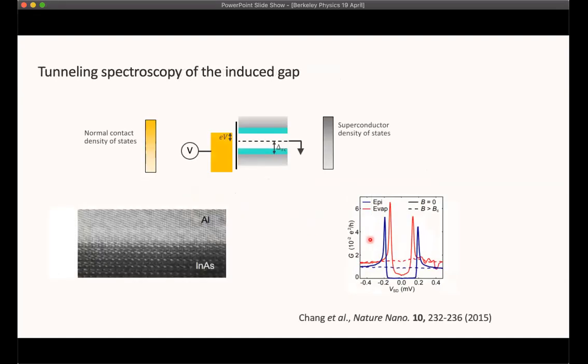And so that's exactly what I was showing you earlier with this induced gap measurement. So now we're probing the density of states of this proximitized, this superconducting semiconductor. And what we expect is some gap that's somewhere between 0 and the parent gap of the aluminum. And that's indeed why we see that the gap can differ depending on the deposition process of the aluminum. And it's an important metric for us to tell us how well we're doing at introducing the proximity effect.